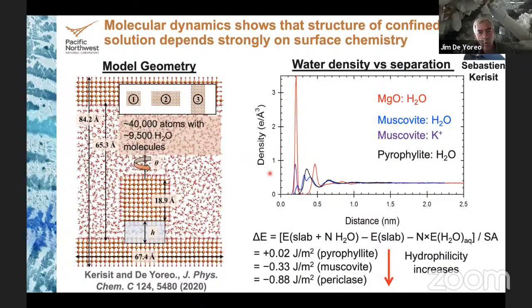So if we first look at the difference in water density versus distance from the surface, for different materials, what you see is that depending on what materials we look at, these distributions are very different. So if we have magnesium oxide, which is the most hydrophilic, we have this very dense layer of water right near the interface. If we go off to pyrophyllite, which is the most hydrophobic or the least hydrophilic, we see this water peak is pushed out further and is not as intense. And in fact, if you look at the energy of pulling surfaces together or apart, you can see that it scales with the hydrophilicity. So clearly, the surface itself, in addition to the structure changing the distribution of water, the chemistry matters as well. And of course, that's not a surprise, but I just want to emphasize this point.